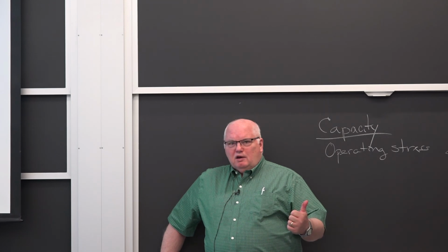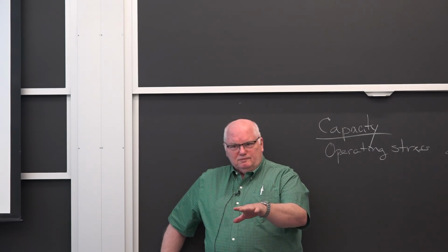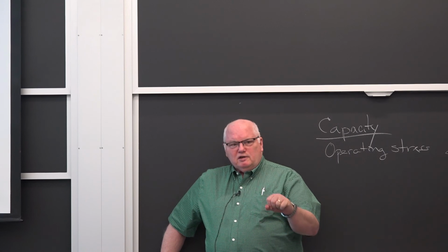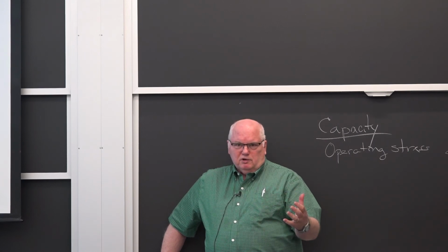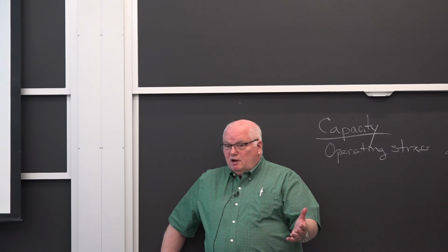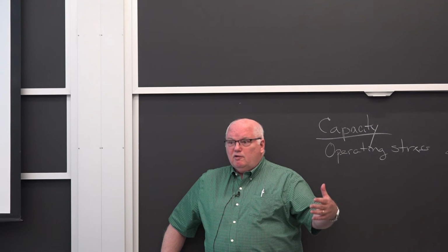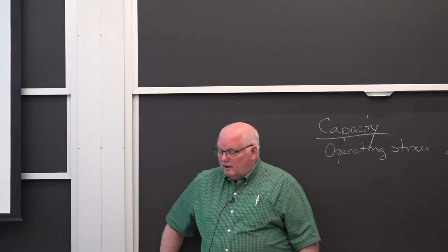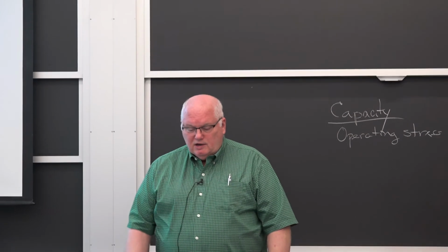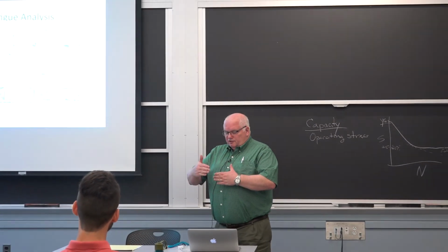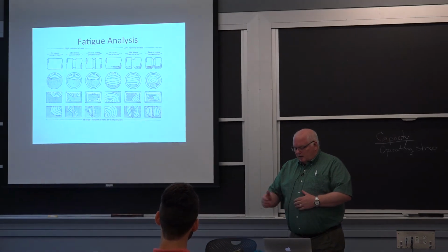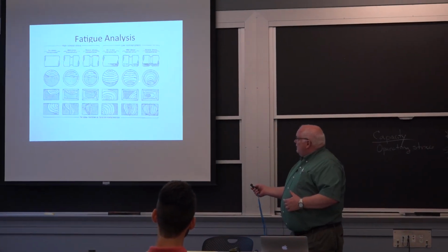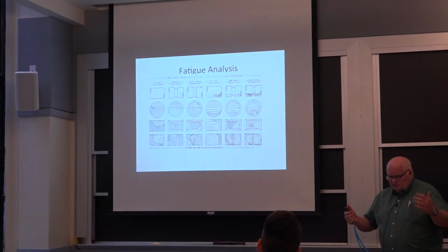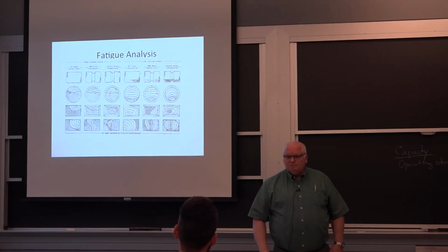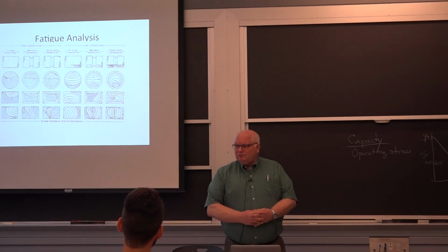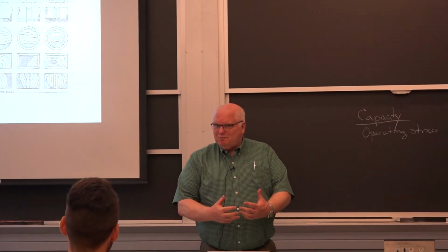Well, you get blue coloring, and the temperature was not uniform with time, okay? You get blue coloring in your steel. They sometimes call it blue brittleness in carbon steels, but they call it temper colors, and the steel actually forms a blue oxide around 600 degrees Fahrenheit. Go look it up on the internet. So I knew the temperature had to be, in some cases, I could see the different striations and I could see the variability. I could tell the size of the high nominal stress, and I think I told them it didn't have a stress concentration, just by looking at the fracture. Sort of like reading tea leaves, right? Except it's knowledgeable tea leaves.